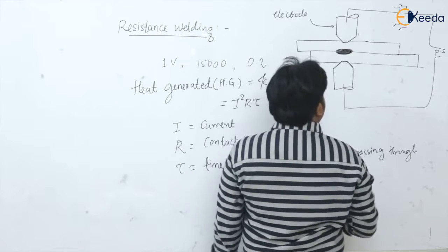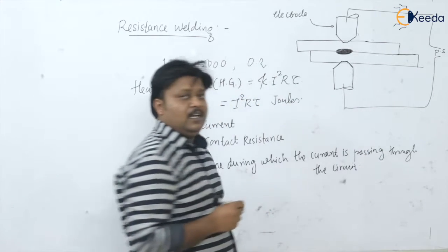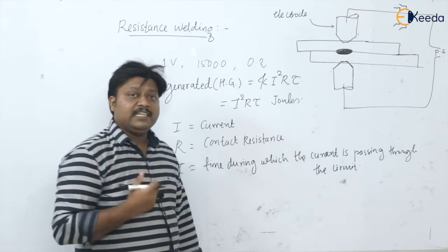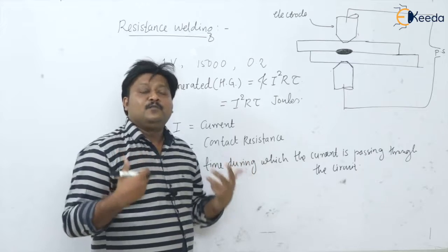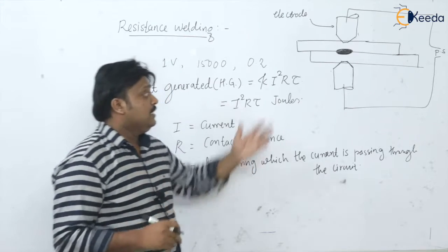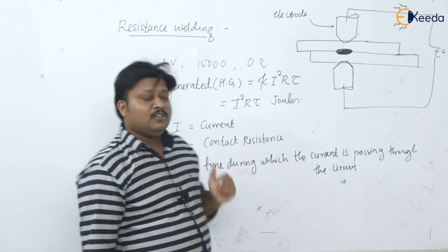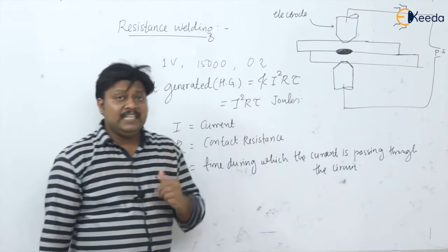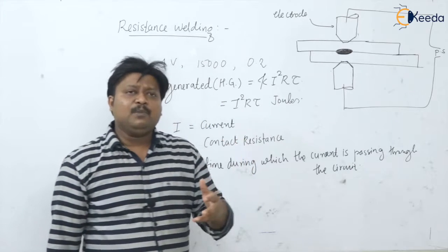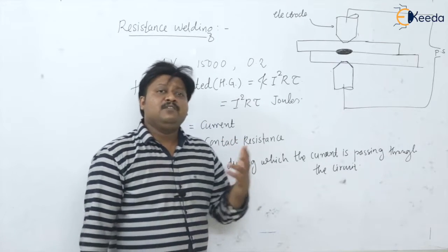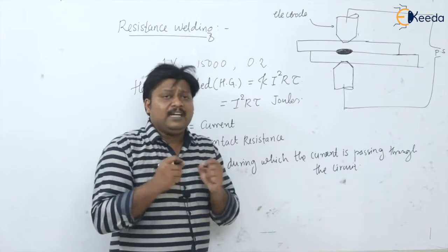Generally the power source is always alternating current, because if this huge amount of current flowed like a DC, these plates would simply melt. So we use an AC power supply with relays, so that in a given power cycle the current will flow only for the required cycles.